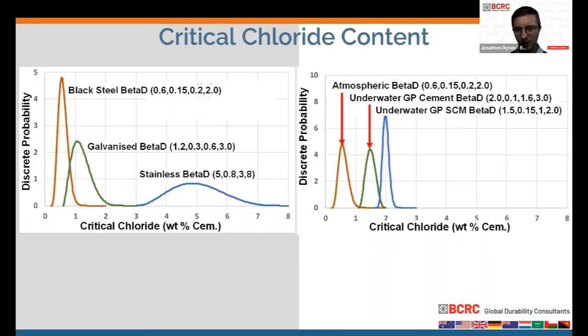And that's been used over many, many years, but that's a single value. And the reality is that, as I'm explaining here in this slide, that's just not reality. It's not always the case that 0.4% is the value at which reinforcement will start to corrode. In some structures, the reinforcement might start to corrode at values down at 0.1%, or maybe even a bit lower in terms of the chlorides by weight of cement.